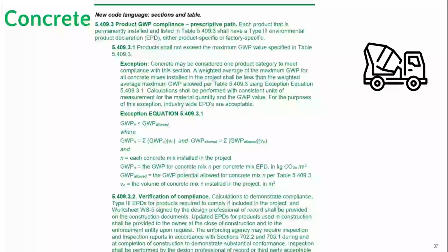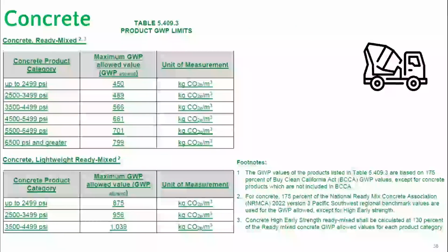And oftentimes when we do that, the GWP of the concrete mixtures are really quite elevated. Or the other side of that is if there's a specific lower water cement ratio required, that has the tendency to increase the global warming potential as well, as generally speaking, you will be using concrete mixtures with higher cement or cementitious materials.